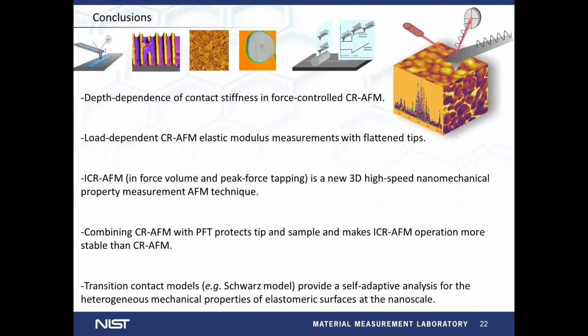So my conclusions are here. We talk about depth dependence of contact stiffness in force control CR-AFM modes. We also talk about using flattened tips in these load dependent CR-AFM measurements, providing more reliable measurements and preserving the tip. Also, better tip preservation is obtained in intermittent contact resonance AFM, and these are new modes that we can accomplish in force volume and peak force tapping. And finally, this transition contact model, the Schwarz model, provides an interesting analysis in terms of both elastic and adhesive properties of the samples.